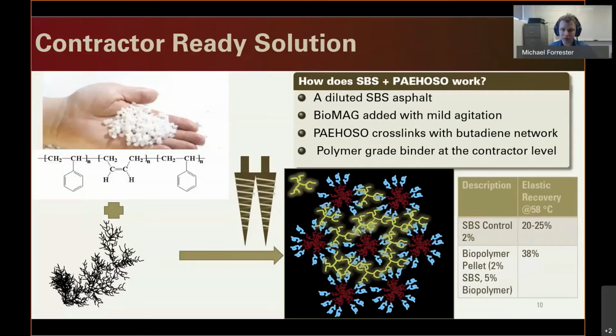So there's still some development that we're working on, and so we're using this system to try to optimize some of the chemistry, get things a little more active so that once it gets into the asphalt, it more rapidly and more fully reacts. But what's really promising about this is that we did see as much of an improvement as we did on our initial tests, and also the ease of incorporation of these polymer systems into asphalt.